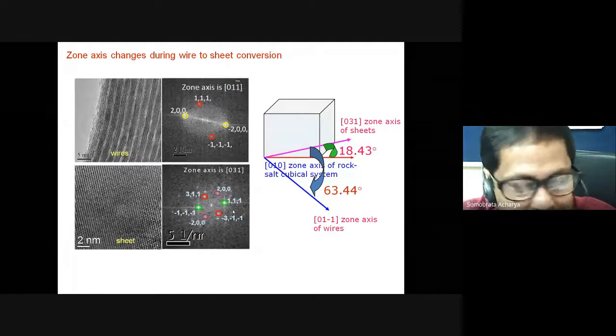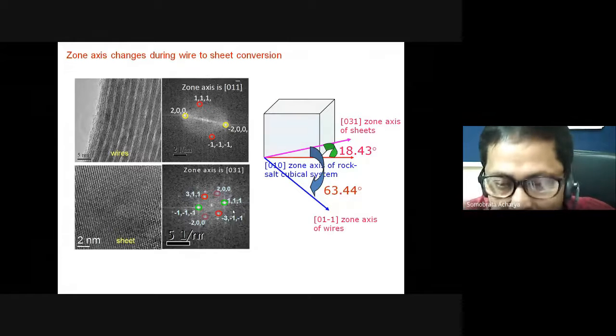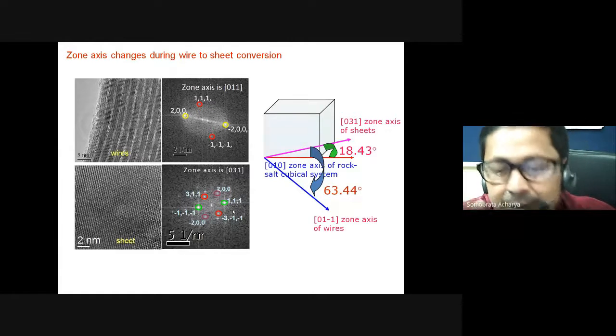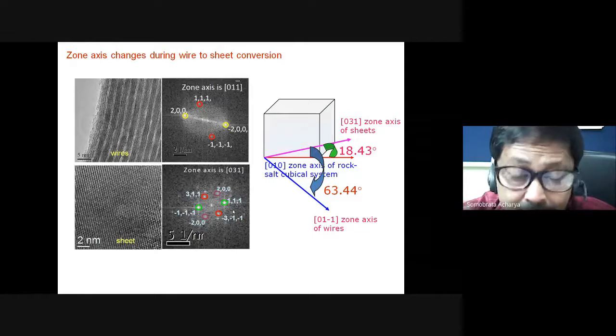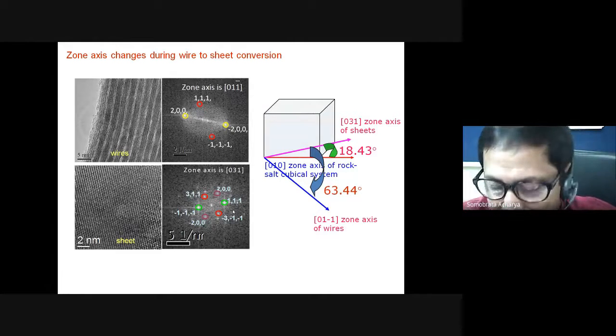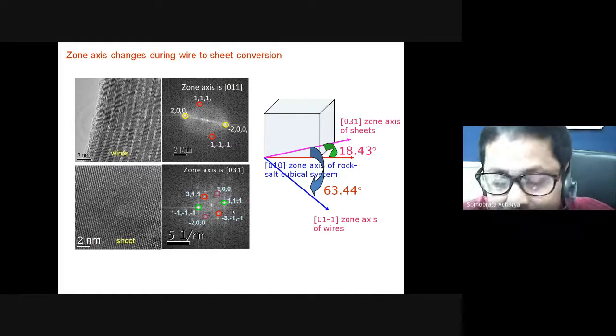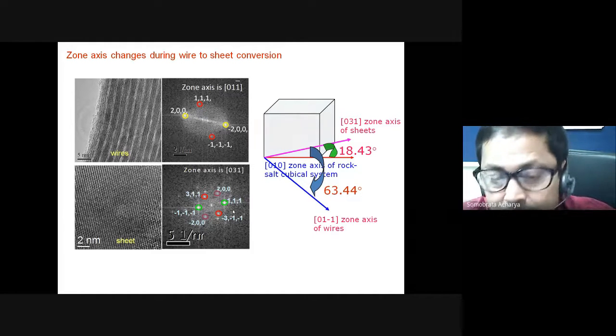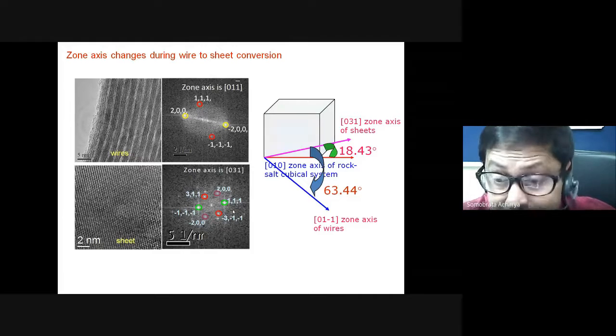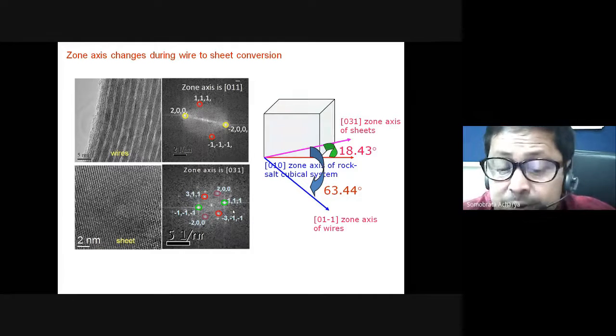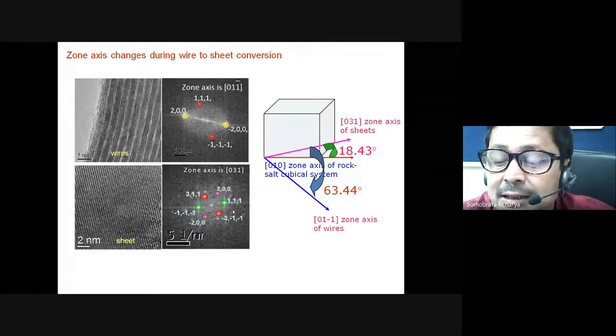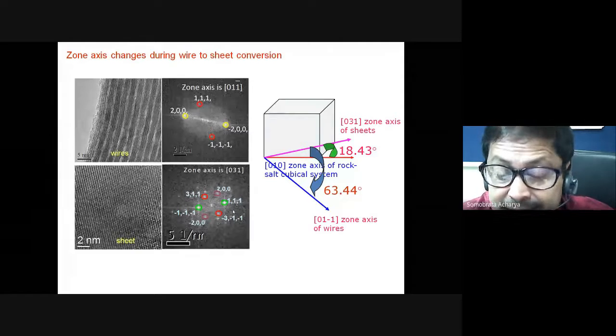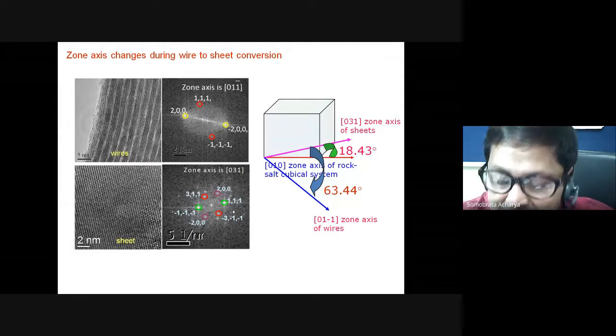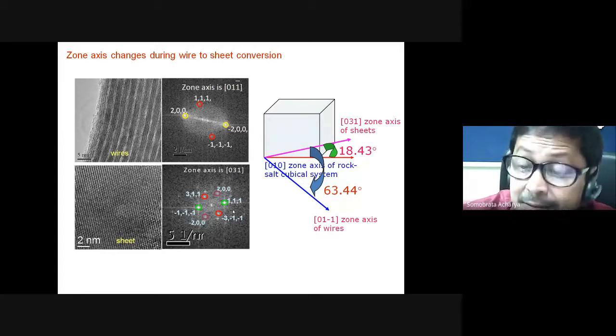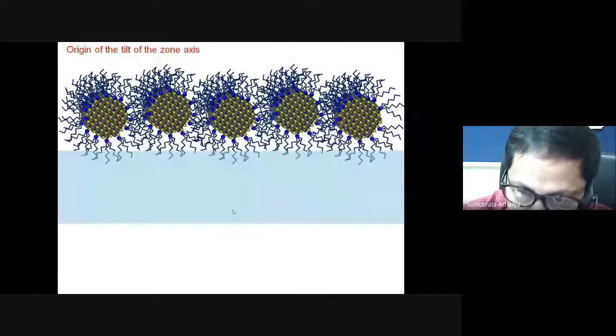You have three different directions, called let's say I, J, K, and then you have two different planes that you have obtained. So if you take the cross product of those planes, then eventually you can calculate the zone axis. Okay. So this zone axis basically will tell you whether this kind of conversion is a straightforward conversion or there is some tilting. So basically what happened is that it tilts.